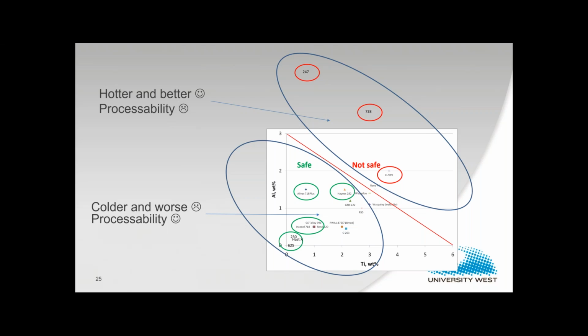But here, additive manufacturing, and especially the powder bed fusion processes, seem to provide a route to explore these more crack-prone alloys that have been impossible to weld by normal welding processes in the past. So I guess one reason for this is the more confined melt pool that you have during the powder bed processes, and also the ability to actually tailor or adjust the melt sequence during processing, which is not as easy for conventional welding processes.